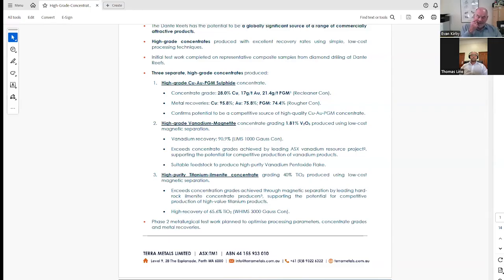It's a magnetite reef system with copper as the main mineralogy, similar to Dante, and platinum and palladium values. The Stella complex had slightly higher platinum and palladium contents, and they would have justified mining without vanadium or titanium production. And in fact, there was very little titanium in the Stella complex. Tom, that's pretty well a view of South African deposits.